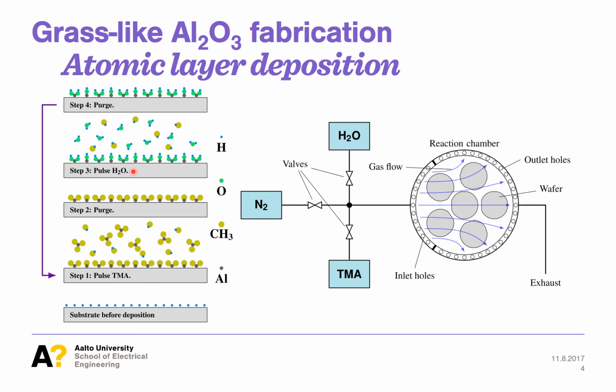Water reacts with aluminum, creating hydroxyl groups at the surface and releasing more methane as the product. After the water reaction is saturated, the reactor is purged again. This is one full cycle of ALD growth. Atomic layer deposition is a stepwise film growth, which allows outstanding control over film thickness.